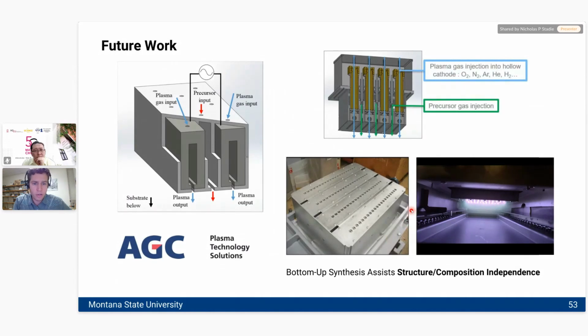This has the potential to revolutionize things, because here you don't make particles and then mix your particles together and put them together at an electrode. You just make your electrode in one direct step directly onto copper foil. And so, yeah, this is research that's ongoing in our group.